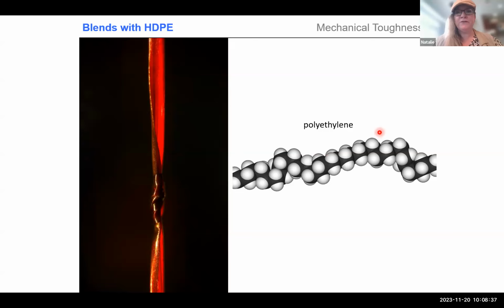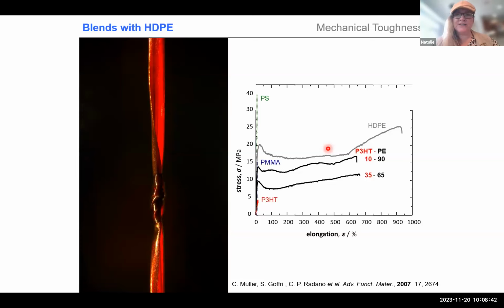So therefore, we have to add something like polyethylene. And just to bring in some material science, you can easily test toughness, so how much energy a material can absorb, from tensile tests. So you stretch, you measure the elongation, and you essentially measure at what stress the material breaks. And here you see if you take polystyrene, PMMA, which is plexiglass, and P3HT of a medium molecular weight, they really break very early, not only with respect to elongation, but also the stress.